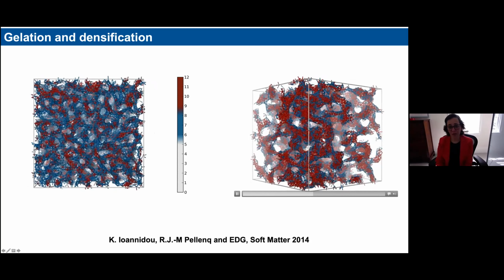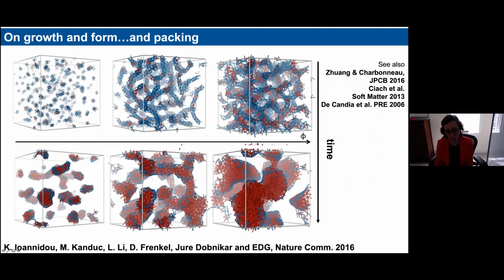So you start to understand a very interesting thing, I think: the sequence of how the interactions evolve over time during the cement hydration has an impact on the development of the properties of the gel, in a way that was not necessarily obvious in the beginning, because the fact that you start from a lower surface charge, where you can have this intermediate range repulsion, leads to a very fast growth of these fibrils, which are favored by this type of interaction.